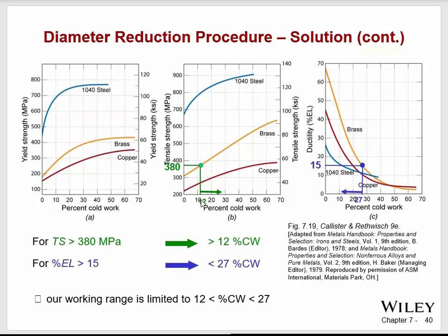So that tells us then that the range we're looking in, and I'm going to use this graph over here to highlight what the region is that we're interested in, anywhere from 12 to 27. That's reasonable, isn't it? For the physicists among us, we have a tendency to maximize this using functions, but that's quite difficult when you're dealing with data like this. I think the engineering approach is to say, hey, 20% is pretty closely in between 12 and 27, so let's aim for 20%.